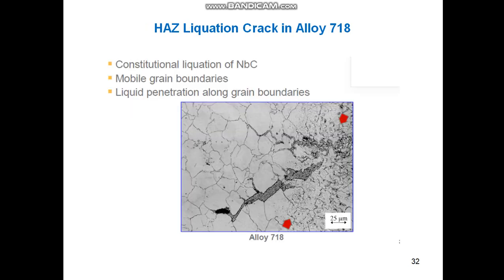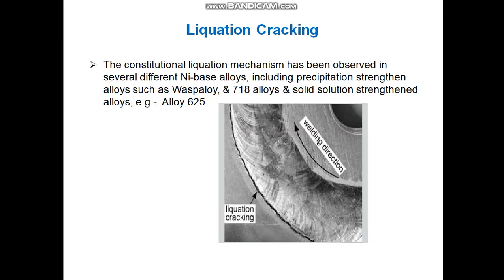and we have partially discussed the liquation cracking phenomena. That's because of the constitutional liquation due to niobium carbide formation. The liquid penetrates through the grain boundary, and under the restraint condition, the grains separate out. Most of that is found in alloy 718.